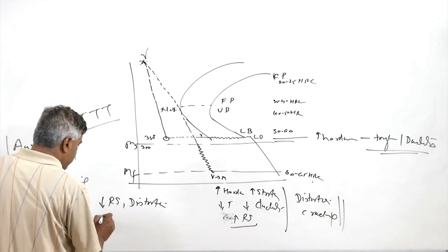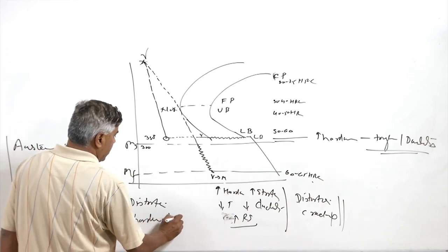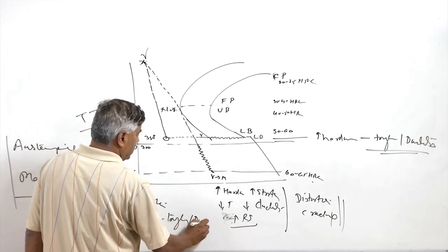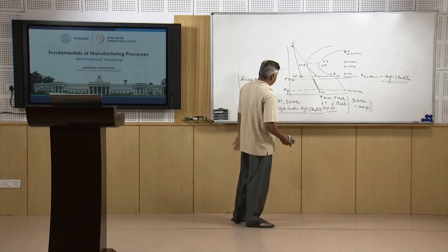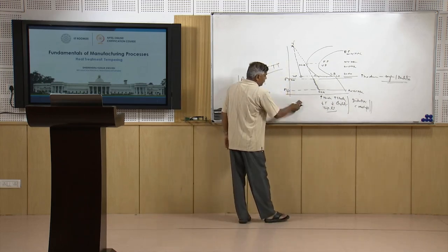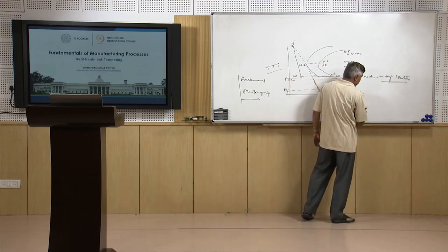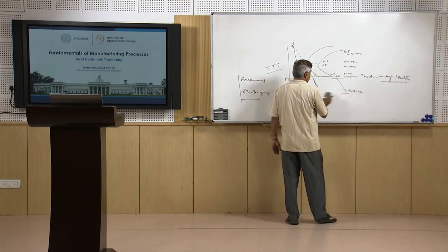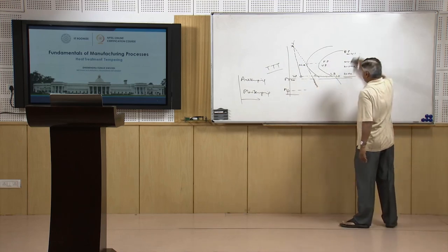So when the bainite is formed, we get very good strength, very good hardness, and at the same time toughness and ductility are also good, meaning these are not compromised very badly in case of Austempering. And the uniformity of the temperature across the section is basically responsible for reduced residual stresses and reduced distortion tendency in case of Austempering. Now the next treatment is the Martempering.